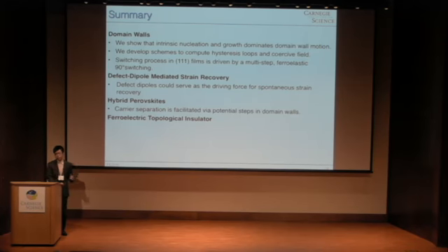That's true, and that's also what we found here. The Landau-Ginzburg value you obtain for perovskite in the nanoscale region, approximately, because the critical size of the domain is approximately, in accordance with Weinreich, 5-10 nanometers, so for this scale you can obtain the real Landau-Ginzburg value. And switching is described by the Landau-Khalatnikov equation.